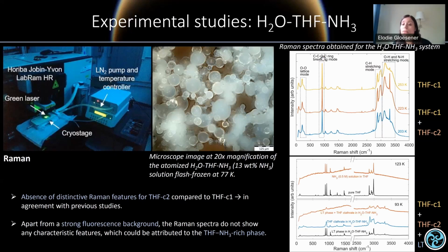The ring breathing mode of THF shows here a sharp peak that is typical also of THF entrapped in clathrate hydrates. So the absence of distinctive Raman features for THFC2 compared to THFC1 is in agreement with previous studies.